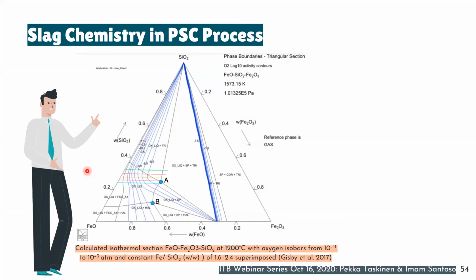So it is important to see the phase diagram with silica in the top corner, and then wustite and also hematite, because iron in the slag can also be formed as magnetite. So this ternary diagram is very good for describing the situation that happens in the slag. And the blue line here describes the oxygen pressure in the system. When it moves to the right, the oxygen pressure is increasing, which means the condition is very oxidizing, right?